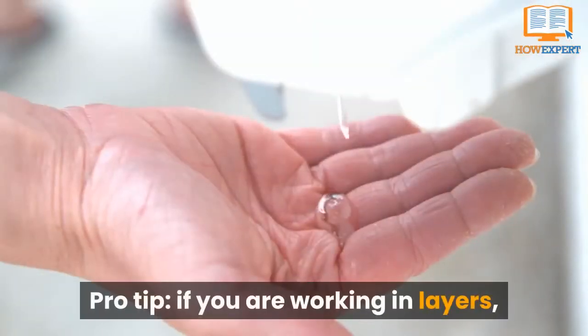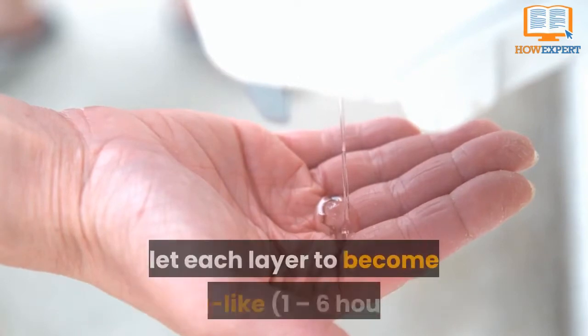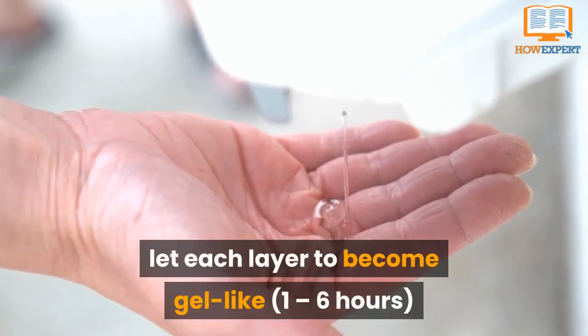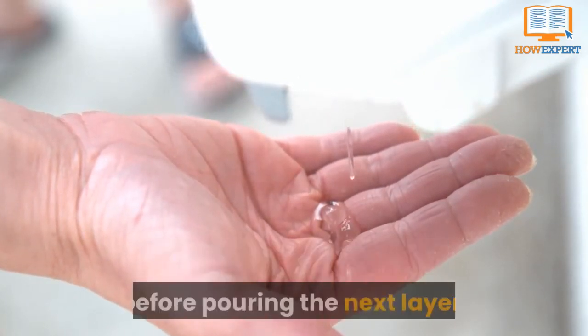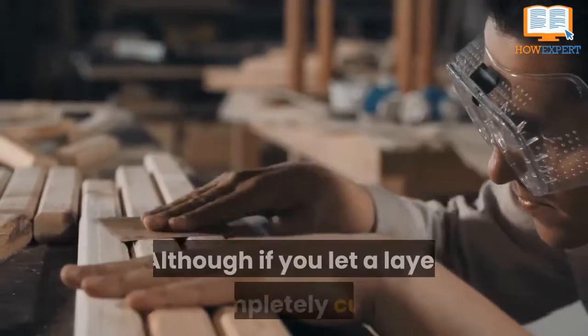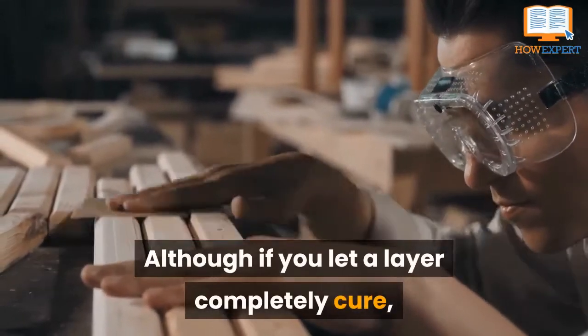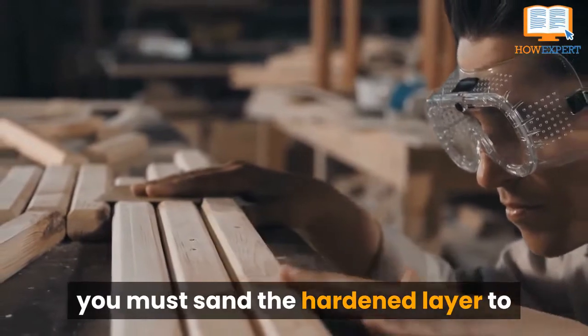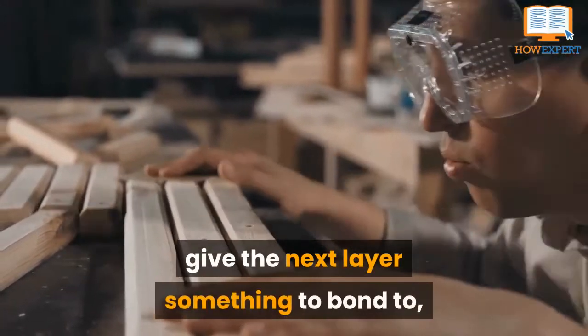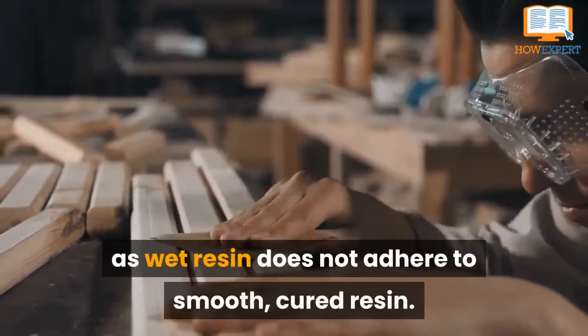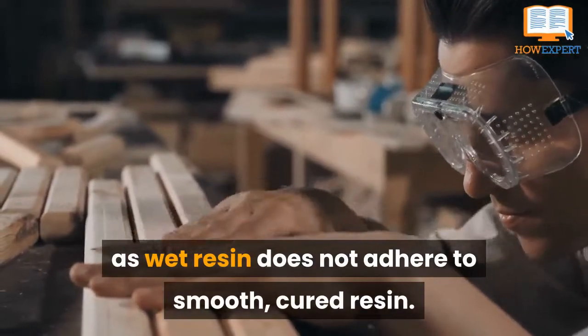Pro tip, if you're working in layers, let each layer become gel-like 1 to 6 hours before pouring the next layer. Although, if you let a layer completely cure, you must sand the hardened layer to give the next layer something to bond to, as wet resin does not adhere to smooth cured resin.